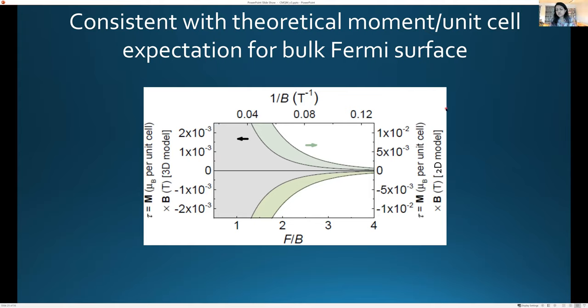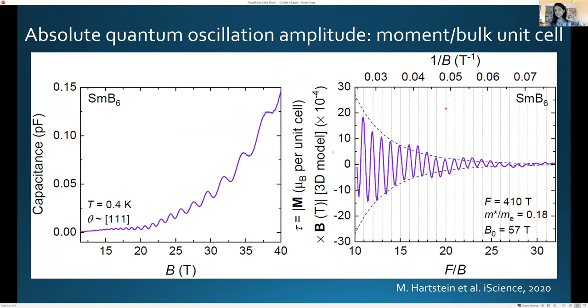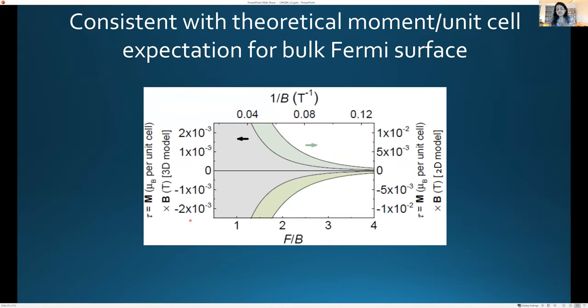In contrast, if we were to associate these oscillations with the surface, it would be about a million times less volume, just because it's a few unit cells, which would mean that each unit cell would have to contribute a few hundred Bohr magnetons. So you just take 10 to the minus 3 and multiply it by, say, a million. Each unit cell would have to contribute a few hundred Bohr magnetons to give you these big oscillations. And that is not consistent with anything we're aware of. It's not consistent with Lifshitz-Kosevich for sure, and it would be extremely startling if you got such a high contribution from each unit cell.